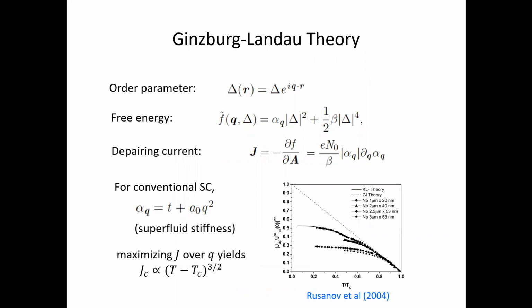Not going into all the details, but this can be demonstrated using the beautiful Ginzburg-Landau approach, which I'm always a fan of. For conventional superconductors, if you express the free energy in terms of the superconducting order parameter, it consists of basically a quadratic term, and the quadratic term involves a constant part, which is set by the critical temperature. And it has a Q squared part, this is the gradient term, and the coefficient of the gradient term is known as the superfluid stiffness. Just from this free energy, we can find expressions for the critical depairing current, by minimizing the free energy and maximizing the critical current.